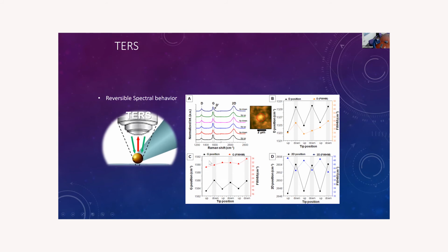For example, you know that in graphene, you have 3 main Raman bands, the D, the G, and the 2D. And all the bands change, but in a reversible way. So I start going and touching the sample with the tip and going up, touching the sample, and I observe that I can make this kind of plot where I always have the same kind of response.